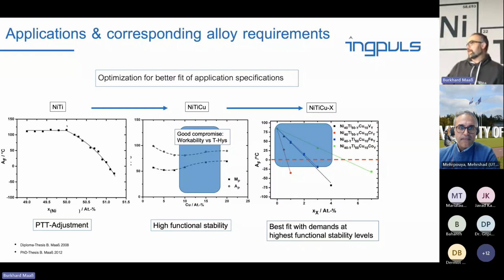One thing of NiTi is also that it has a rather large hysteresis. How do we get the hysteresis small? By adding copper. This is also nothing that we invented. That's been in the literature since the 90s. But then if you look at the literature, then you learn that if you put in a lot of copper, your material gets brittle. So you get a good functional stability because the crystallographic compatibility between austenite and martensite becomes better.